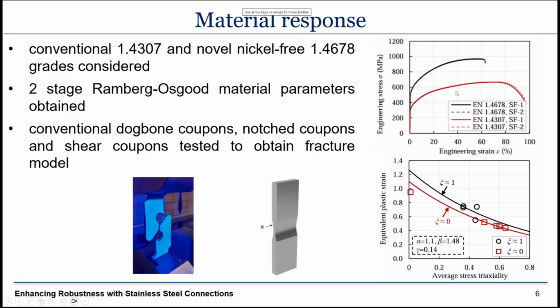So we conducted a number of tests on traditional dog bone shape coupons to obtain the stress strain curves. And we, or Imperial College, conducted a number of tests on specially built coupons to obtain the fracture characteristics under a range of stress triaxialities. So in addition to dog bone specimens, also plate specimens with a notch were tested, and also specimens like this one, which induces failure under shear, were tested. This allowed the calibration of a fracture model, which was used later on in the numerical modeling of the connection tests.